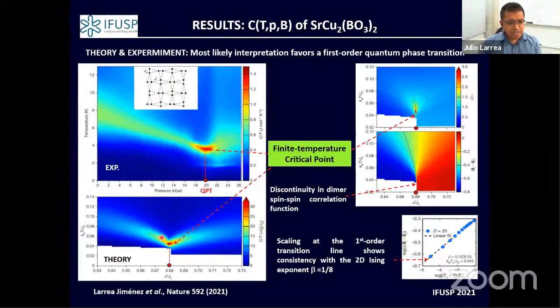If you see another consequence of this theoretical calculation, the first one is that our experimental phase diagram here is a color map representation. We are plotting the pressure, or the intensity of the heat capacity over the temperature, as a function of pressure, where here the most intense peaks in the specific heat are at the quantum phase transition.